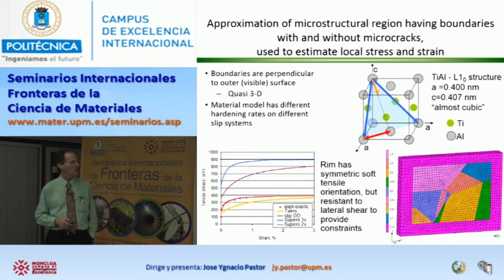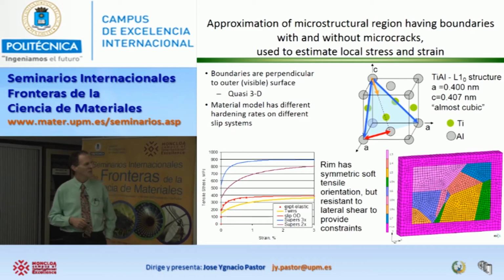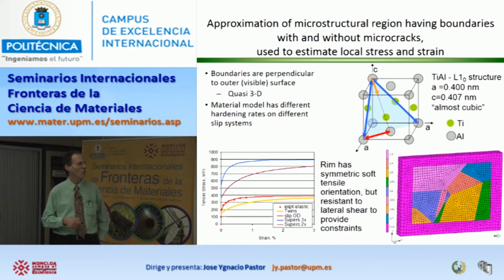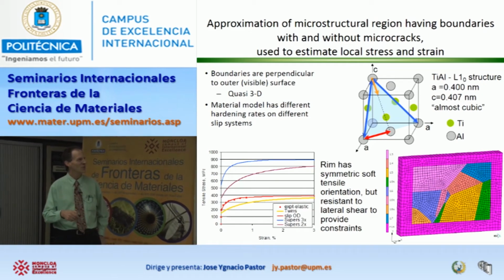Well, first of all, TiAl is not something most people are aware of. Some people have seen it. It looks sort of like face-centered cubic, except it has alternating layers of aluminum and titanium, aluminum and titanium. And the implication of this is that instead of having normal slip like we do in an FCC material, where we have three different slip directions on a 111 plane, we actually have very different things in different directions. In these directions, which go across layers, it's actually difficult to move a dislocation because we have to go two hops before we restore the crystal order. But in this direction down here, we can just do a normal or ordinary dislocation slip. So that means in this material, we have easy slip in this direction, but difficult slip in the other two.